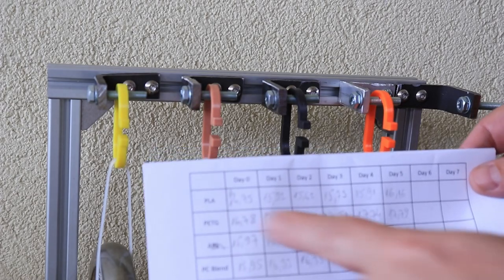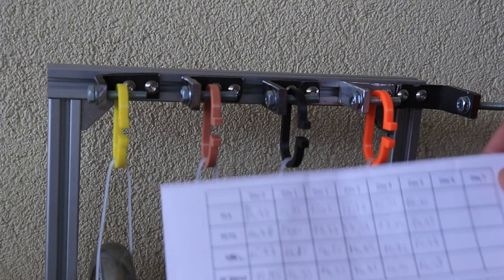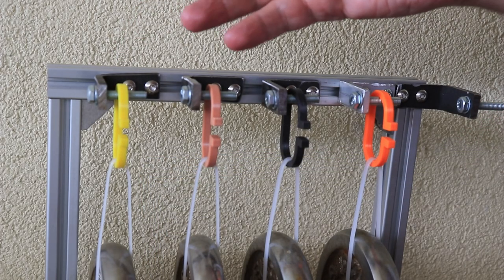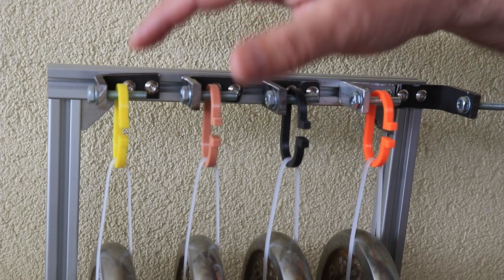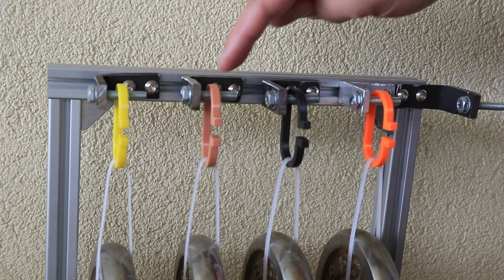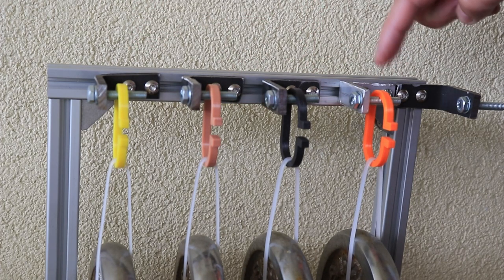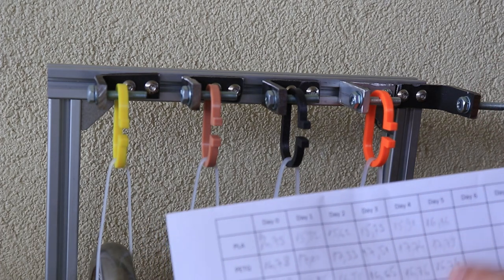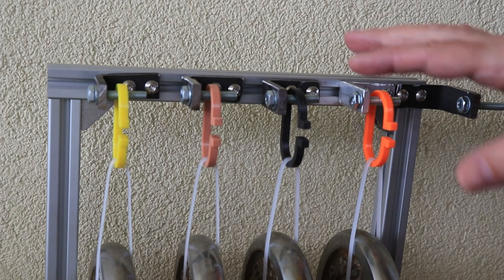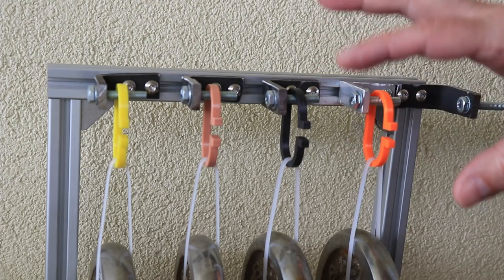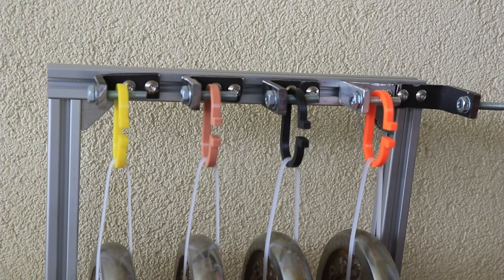This is the 5th day and I measured everything, and so far it looks like the PLA has the smallest deformation, but it didn't stop with the creeping completely. PETG, ASA and the PC blend have stopped with the creeping, almost no deformation at all. But now everything goes into 50 degrees Celsius in the oven for 1 hour.